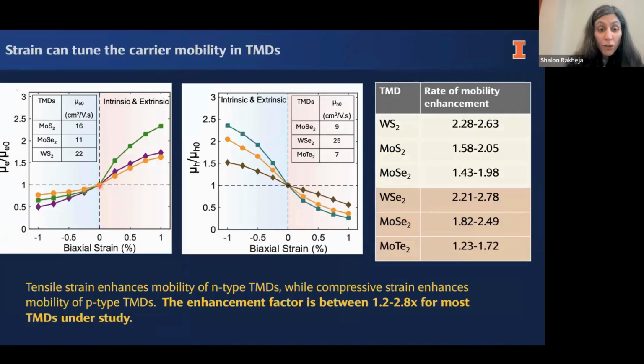For N-type materials, if you look at the orange shaded region, which is my positive direction of strain, my direction of tensile strain, I can see that my mobility increases as my tensile strain is increasing. Now let's turn our attention to the middle graph, which is for P-type TMDs. We can see that for P-type TMDs in the blue region, where I have negative or compressive strain, their mobility increases. So for N-type materials, if we want to improve their mobility, we really have to stretch them. For P-type materials, we have to compress them.